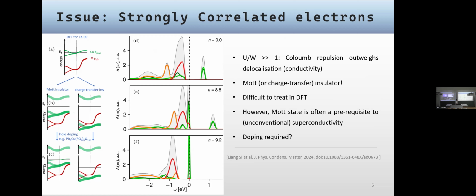why from the theoretical point of view the famous LK99 didn't prove to be any kind of superconductor. It is necessary to recap to understand the point of the idea. So those flat bands on the Fermi level are great if they are actually there, because sometimes the strongly correlated effects in terms of electronic structure may actually lead to an opening of an insulating gap. In this case, I'm talking about Mott or charge transfer insulating nature, which is, as is known, difficult to treat in terms of density functional theory, and this nature was predicted in the LK99 case with the help of more advanced methods like dynamical mean field theory, for example.